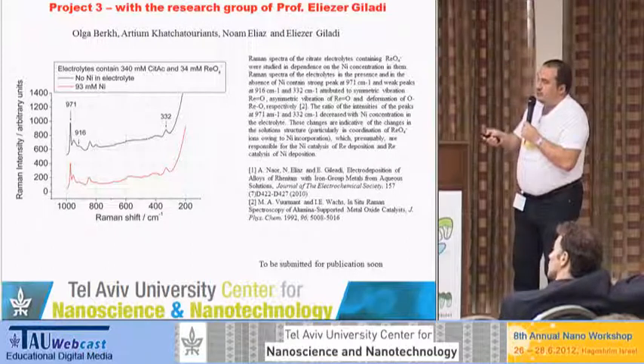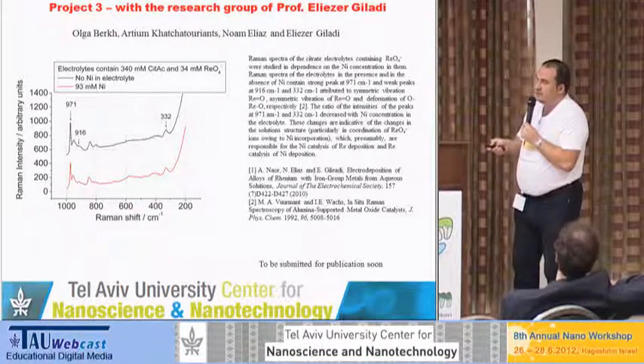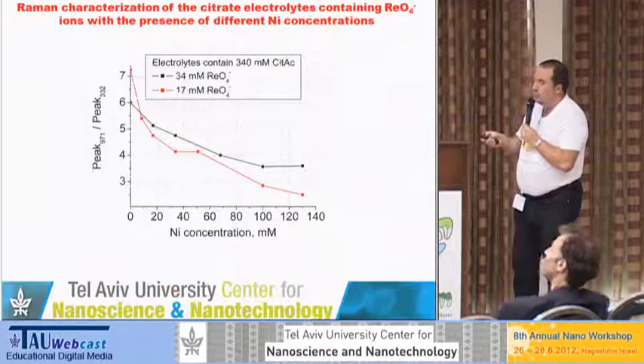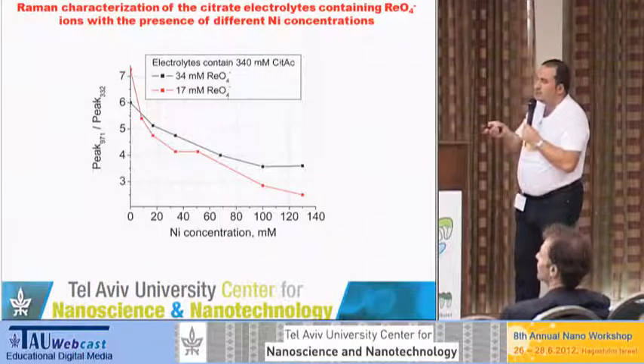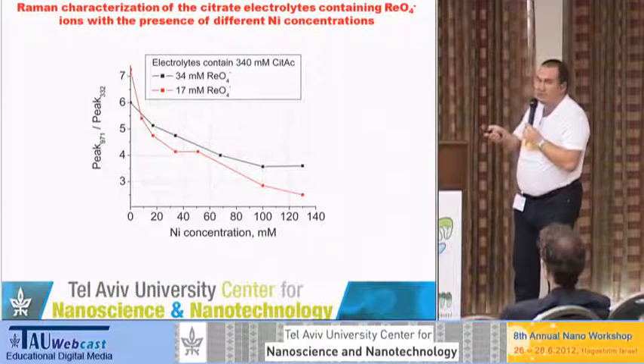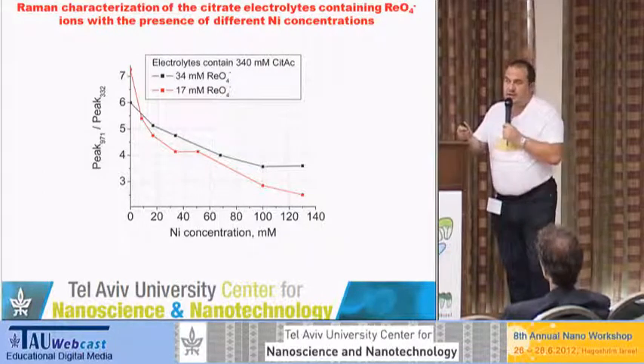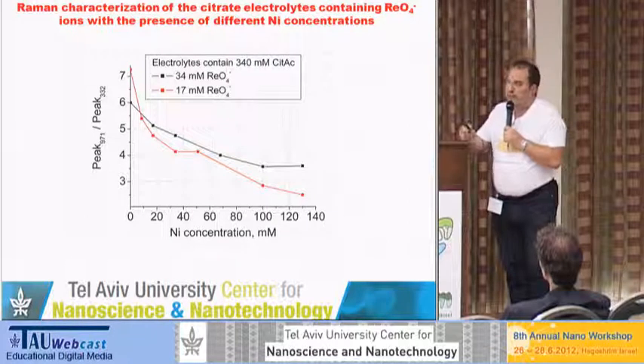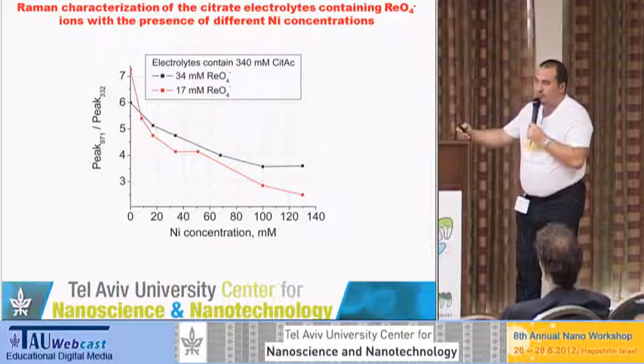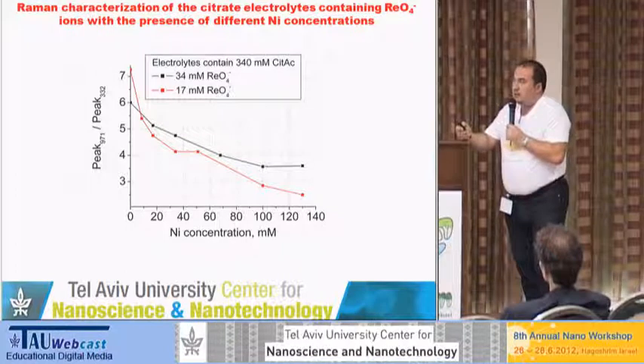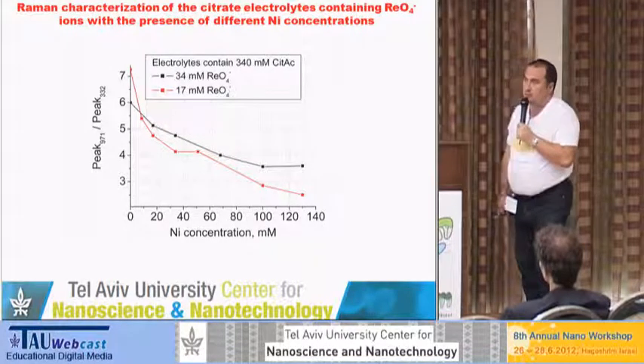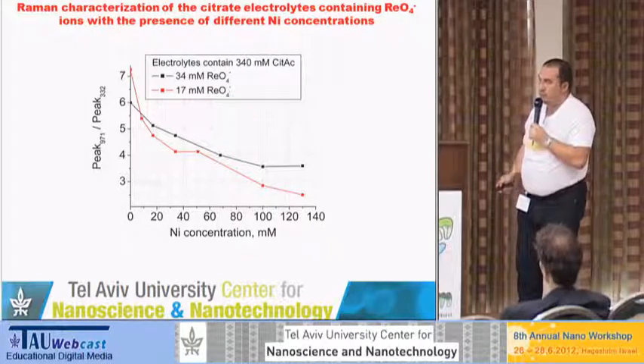And for example, here on this graph, you can see that for different nickel concentrations, the ratio between 971 and 332 is different. And indeed, we were able to follow that when nickel concentration is increased, the ratio between these 2 peaks is decreased. So it gives us an indication of which bond in the ReO4 ion can be responsible for the interaction with nickel, and of course we are now going to proceed with this project and to investigate it in more detail.